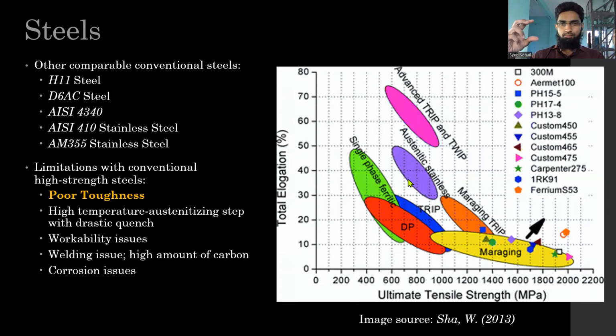Workability issues. These steels, although they offer high strength, are not workable in the sense of cold working or hot working or welding even. So all these things, even some other forming operations. So workability, we club it together as an issue with these steels. They work harden. That's the drawback. You have welding issues because of the high amount of carbon added, more cracking and issues thereof. Corrosion issues as well. So these are the problems with these steels. High strength steel, yes, but with some limitations. Well, many.